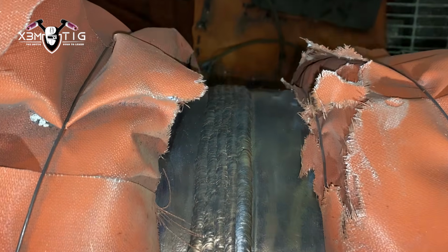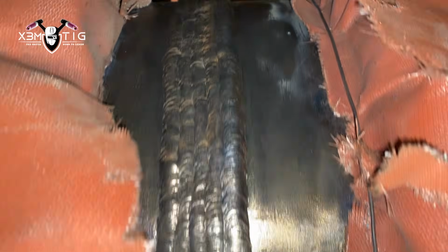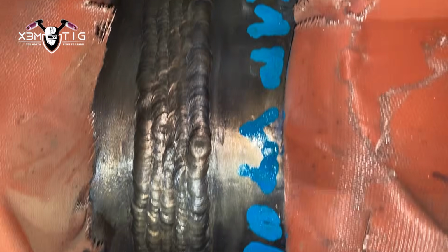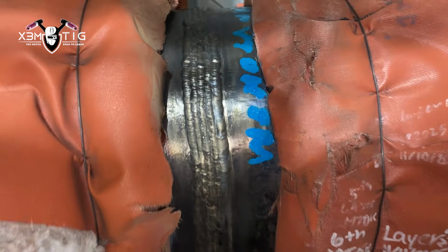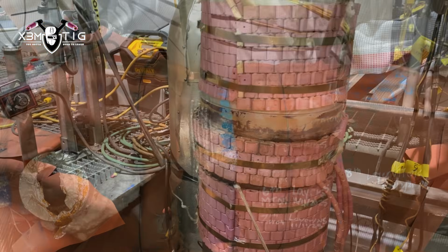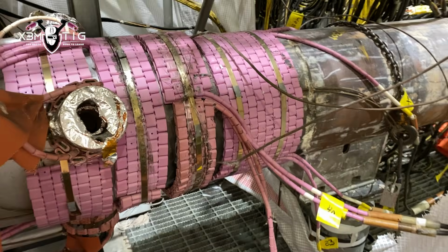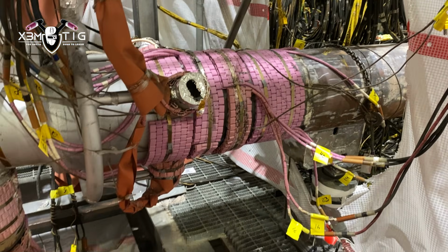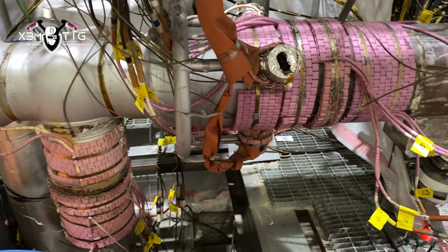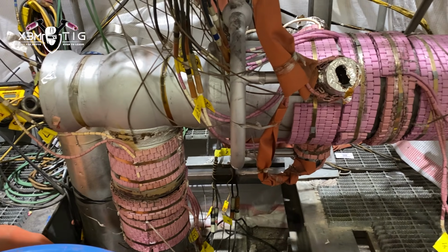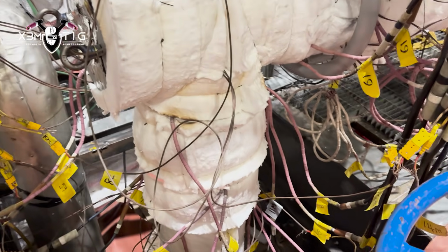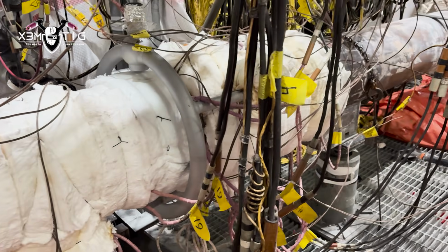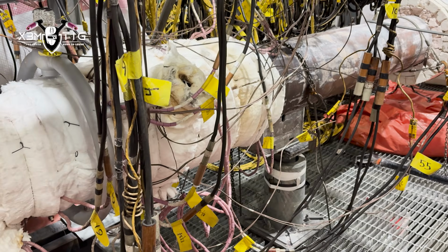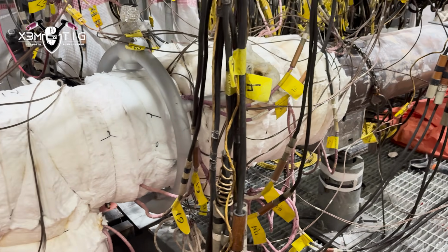As I said, this is like 5-6 days of work, guys. Day shift, night shift. There's lots of testing: MT, PT, X-rays. There are like 8 X-rays on those 2 joints. So this is a post-weld heat treatment. It takes about 2 days to set up for that procedure, and after that's done, they're going to do bake out. Same thing, the bake out procedure, and then you've got to call it off in sequences. They've got to keep it.